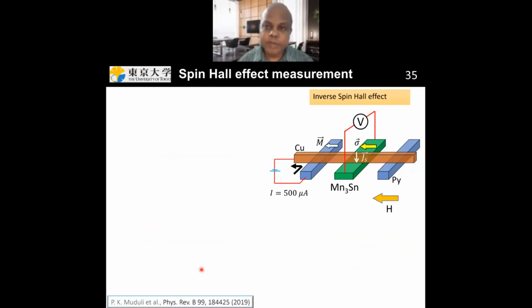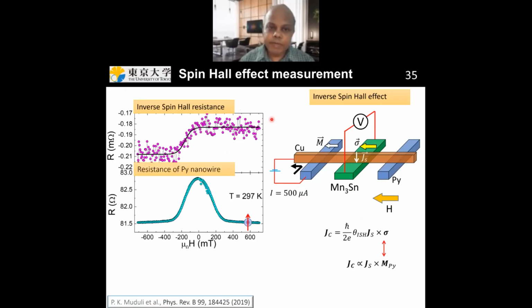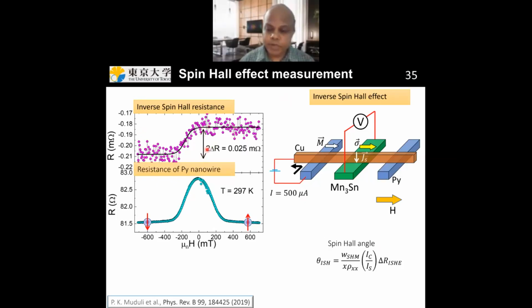After that, I did the inverse spin Hall effect experiment, in which you inject a spin current, suppose with spin polarization along this direction, by applying a magnetic field along this direction. Then you get a finite resistance over here, and then you reverse the magnetic field, which reverses the spin polarization direction of the spin current, and you get another resistance. By measuring the difference between these two resistances, you can calculate the spin Hall angle using this expression over here.